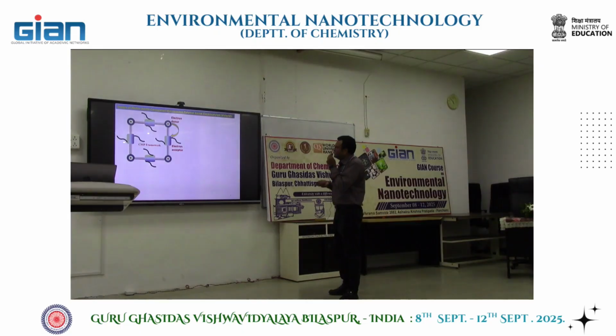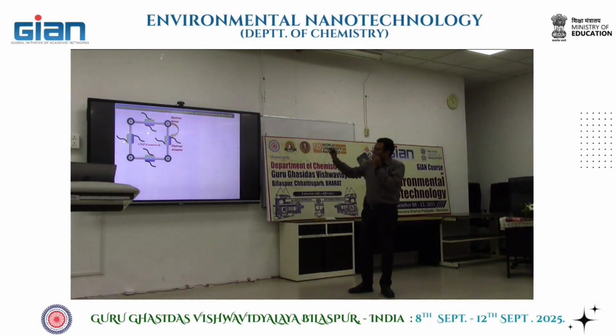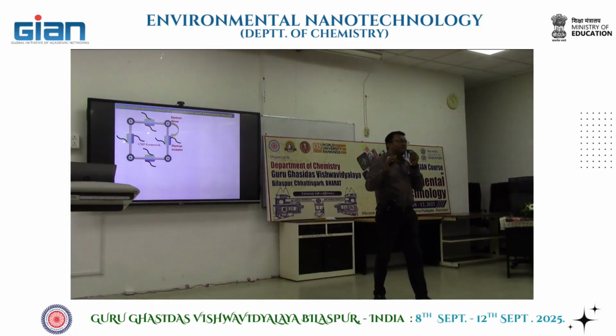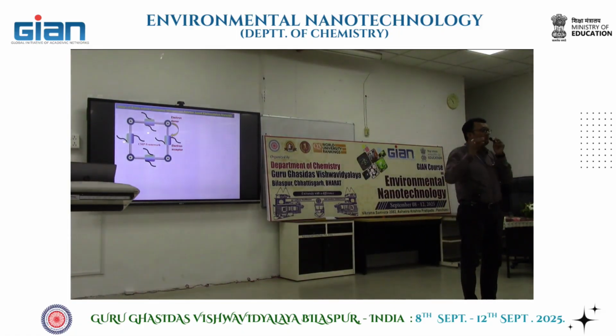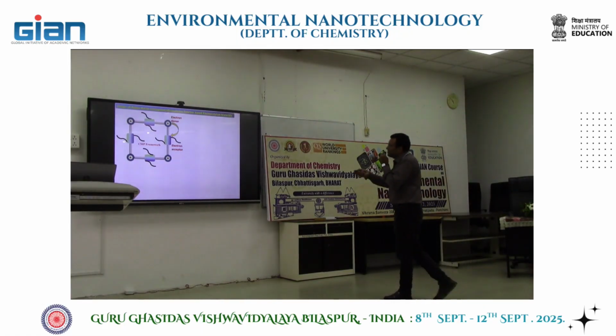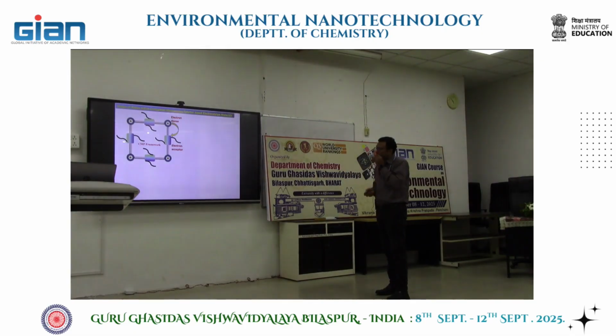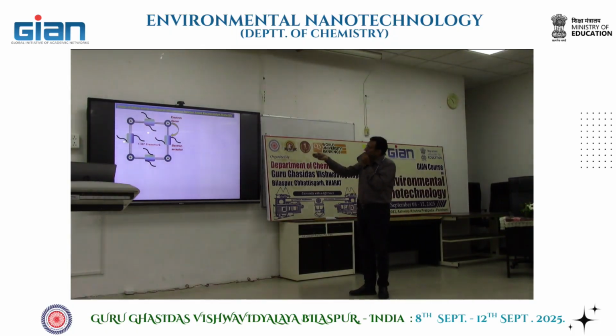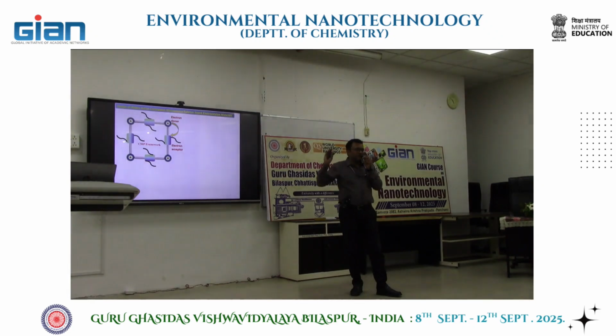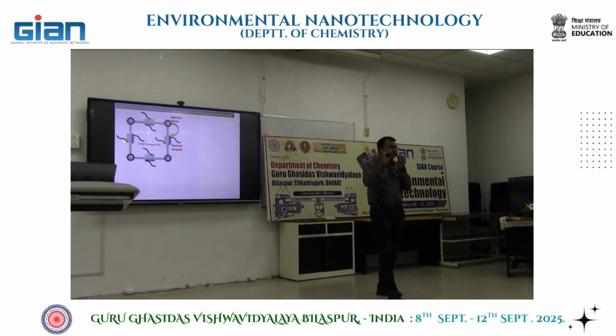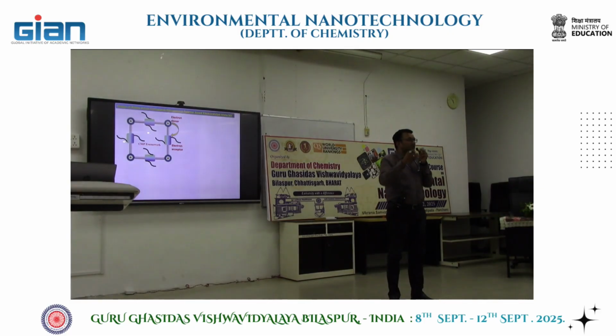Now I will focus a little bit on the basic design of the molecule in order to get the property which can perform oxidation reduction reaction as well as evolution reaction. So if you consider a conjugated microporous polymer, which the name itself suggests, the first term is conjugated redox active. Redox active means you have to have two units where one acts as the electron donor and the other acts as the electron acceptor, right? Then only can you get the redox active properties.